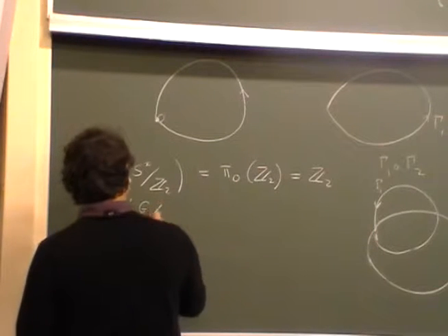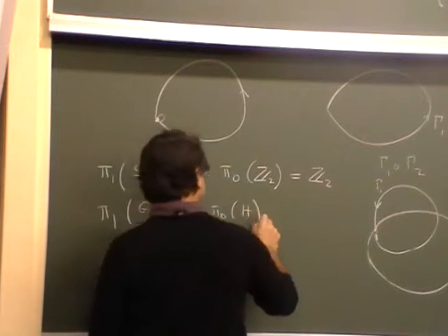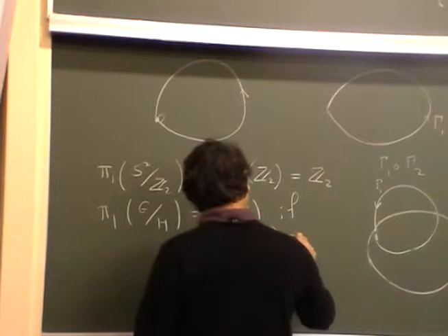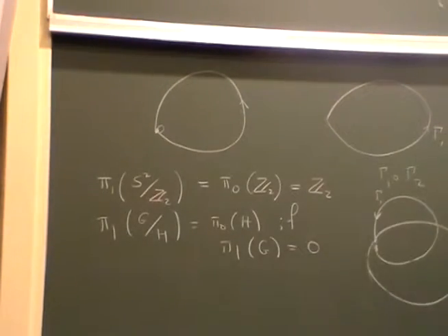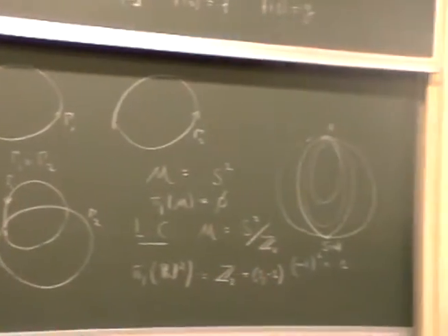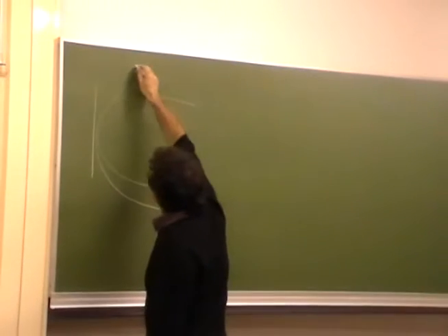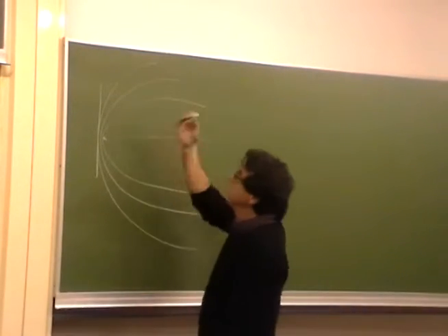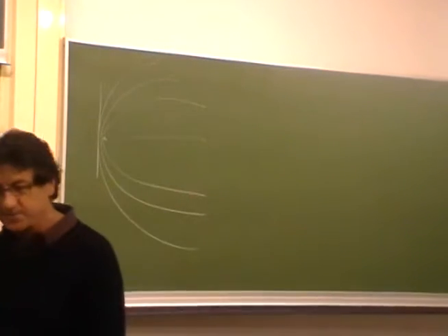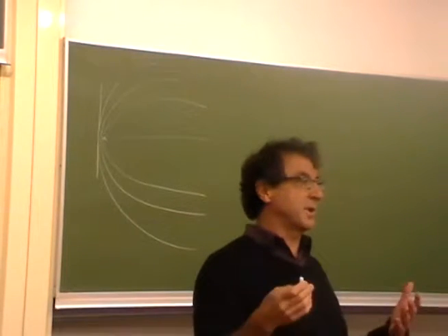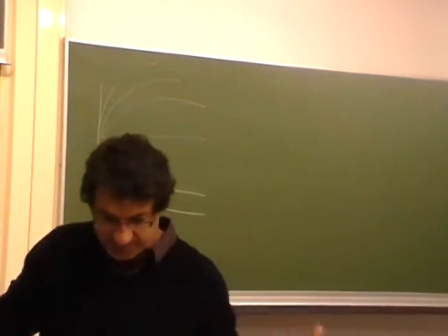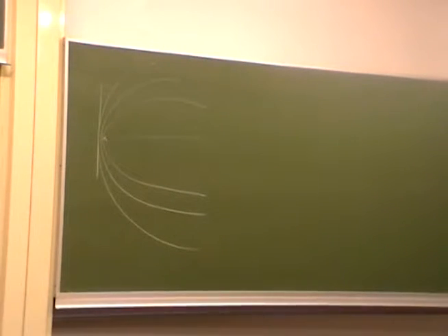The pi 1 of G mod H is pi 0 of H if G is simply connected. So we can use that to get a formal proof, but we showed it here. So there's some non-trivial class of defects, which we saw one kind, plus 1/2, looked like that with a defect here, continued into 3 dimensions. And Urosh showed how you could deform the plus 1/2 into the minus 1/2, and the integer defects are topologically trivial. If you can escape into the third dimension, you can eliminate them altogether and deform to the identity. We'll see something different in 2 dimensions in a minute.